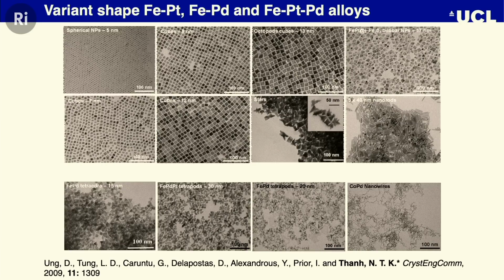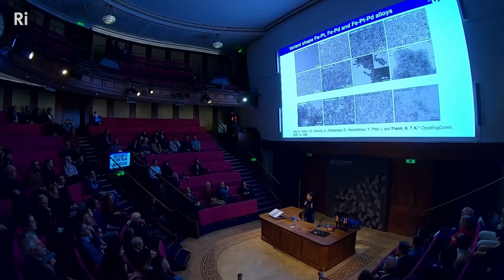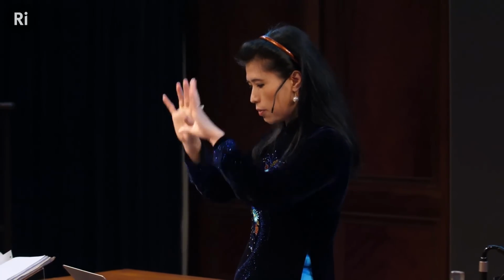But when I started this work, the reason I made different shapes was that gold nanoparticles are used for immunolabeling inside the cell. If you want to study different events, you need three different sizes of nanoparticle, because organelles within the cell are very small, so the nanoparticles have to be quite small. So you cannot distinguish 5 and 6 nanometer, because they are the same population. The best you could have is 5 nanometer, 10 nanometer or 20 nanometers. So my idea was, okay, if we can make different shapes, then you can see them very clearly under the microscope. That was originally why I got into those shapes early on in the work.